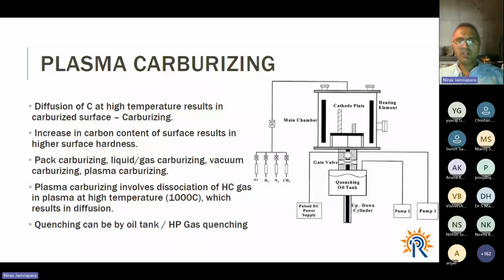It calls for quenching, which results in martensitic transformation on the surface, and higher carbon further adds to the hardness. Pack carburizing, liquid carburizing, gas carburizing, and vacuum carburizing are already established processes, and they have their own pros and cons. Plasma carburizing is a novel process which is very eco-friendly and has a very low carbon footprint. Plasma carburizing involves dissociation of hydrocarbon gas in plasma at very high temperatures, 1000 degrees, which results in the diffusion of carbon from gas to the substrates.